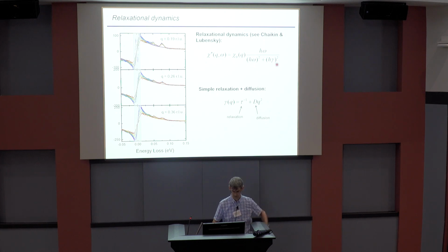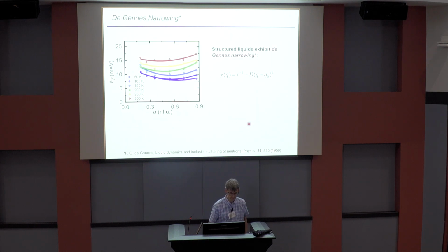Gamma is a scattering rate. And in a system that has relaxation and diffusion, gamma should have just a tau to the minus 1 plus something like Dq squared. So tau is a relaxation rate, D is a diffusion constant. And so we can fit the data at all momentum everywhere in the Brillouin zone with a formula very close to this. And what you get, this is the interesting thing, so this is gamma. And gamma is temperature dependent and it's Q dependent. And so red is 300 Kelvin, purple is 50 Kelvin, and in between it changes.